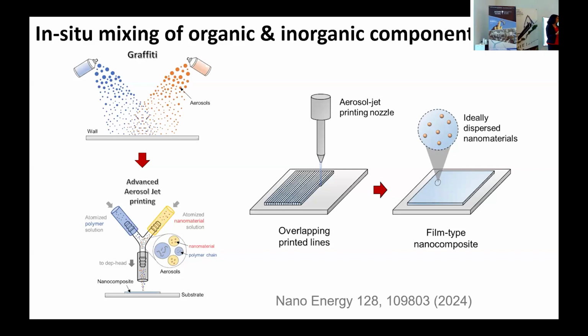This is particularly important if you're working with electronic components, where having surfactants or interfaces, or just having clumping of nanomaterials, can be a problem. We see none of that because this mixing doesn't happen physically. This is actually happening in spray. And we earlier published some work showing how you can get things like high-K dielectrics using this technique.